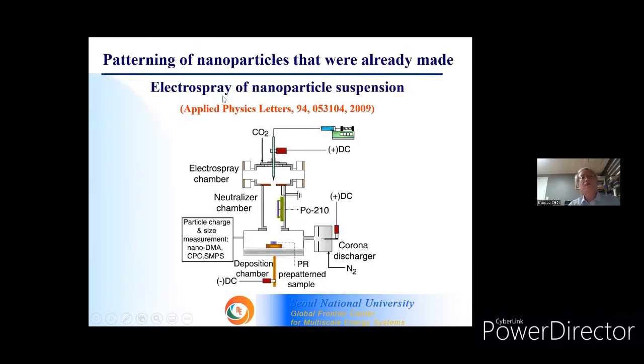You can use electrospray of nanoparticle suspension to generate charged aerosols, but you have to be very careful, since electrospray of charged nanoparticle suspension usually generates charged aerosol with excessive charge. Then if you apply an electric field, particle velocity, even for 10 nanometer or few nanometer particles, becomes excessively high, and they could not follow the focusing electrostatic field.